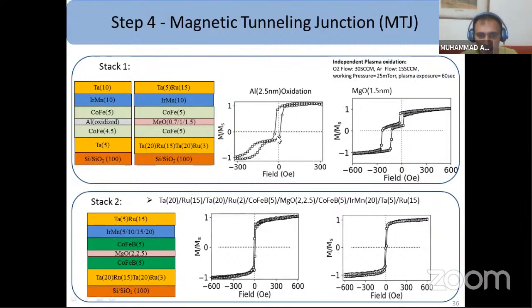Here you can see the antiferromagnetic states. Then these are the saturation states. For MgO, here you can see I did it with the cobalt iron. This is a static characterization.